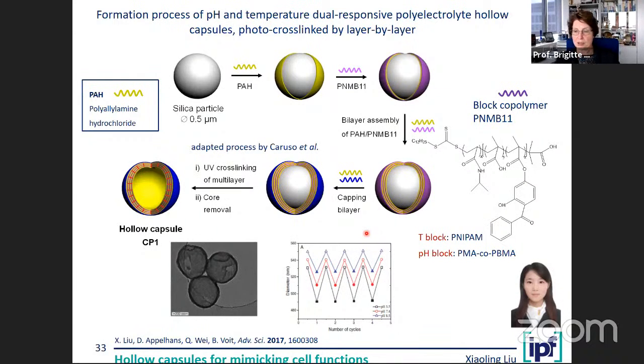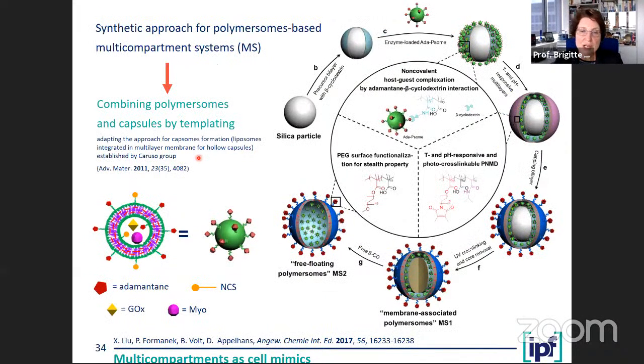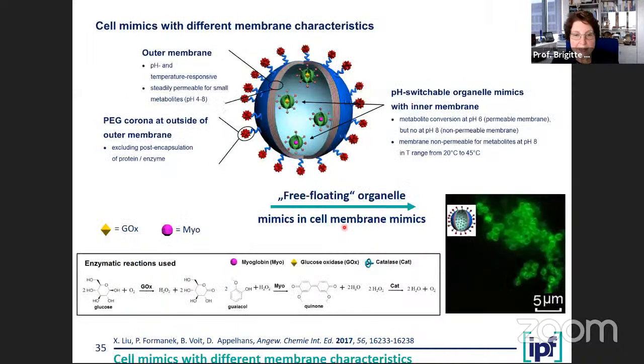One part still I wanted to show you here is a complex one. I showed you the layer by layer approach to make the capsules, and that is used to make a very interesting multi-component compartment. And I will not really show you how the chemistry works. It's quite complex, but in the final state, we were able to have lots of polymersomes in such a larger compartment. And the polymersomes had all been loaded with enzyme, and you can nicely show that those materials actually work and interact. Also, when you have encapsulated several enzymes, you get also cascade reactions in such a large compartment. And we are quite proud about that possibility.